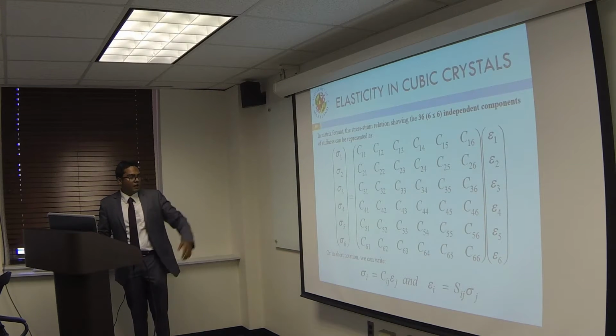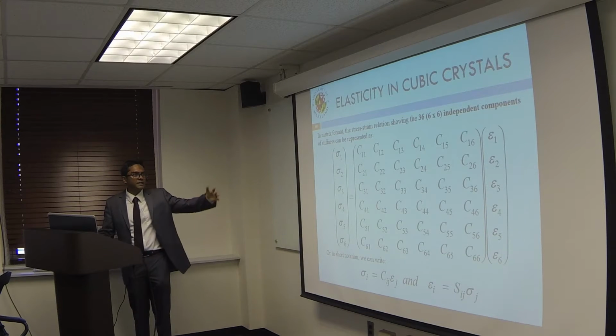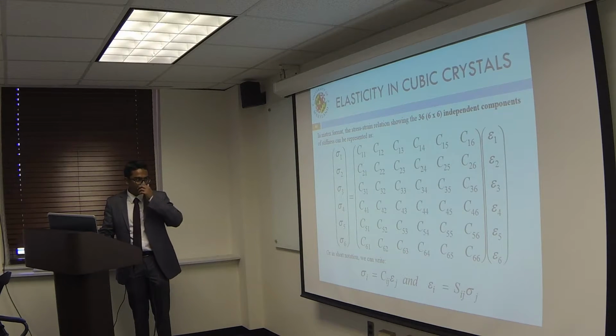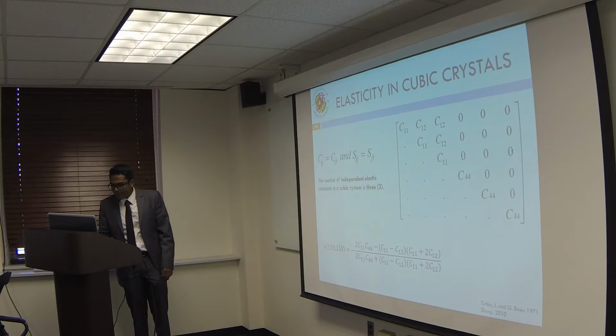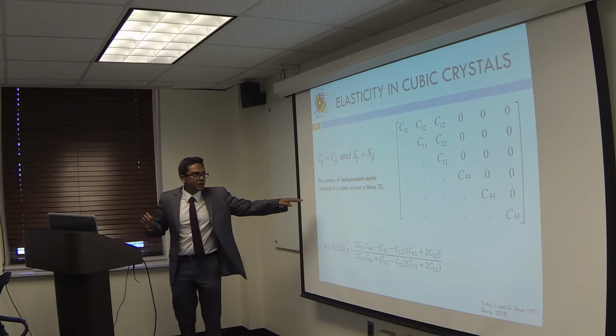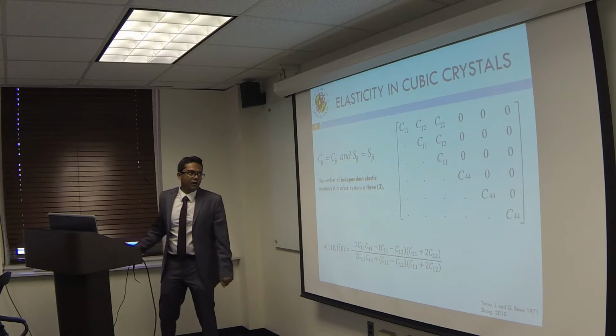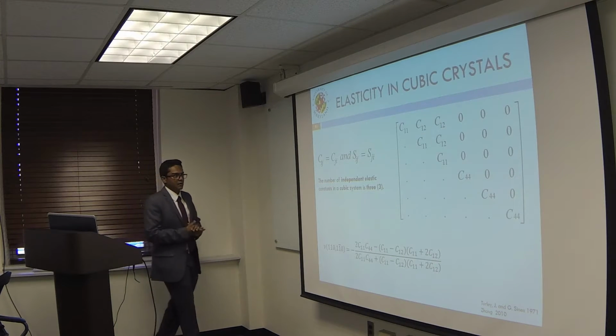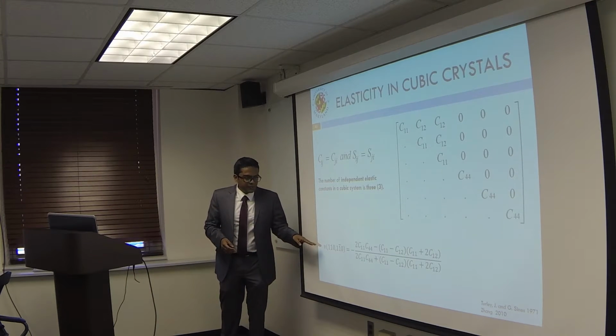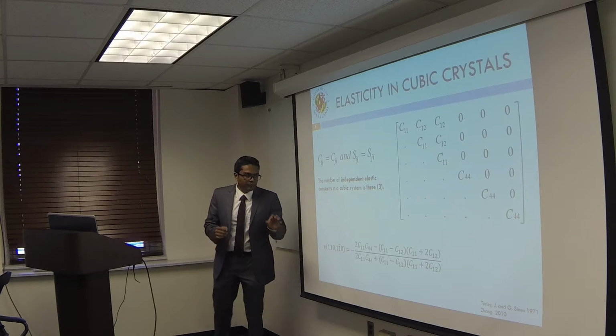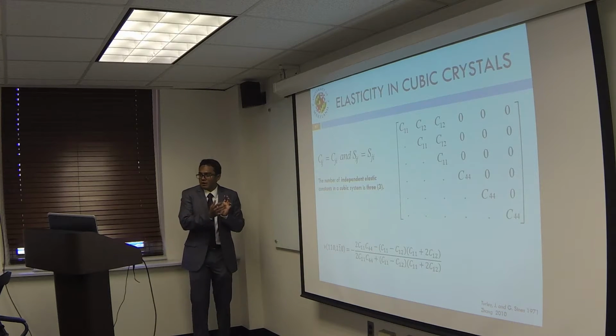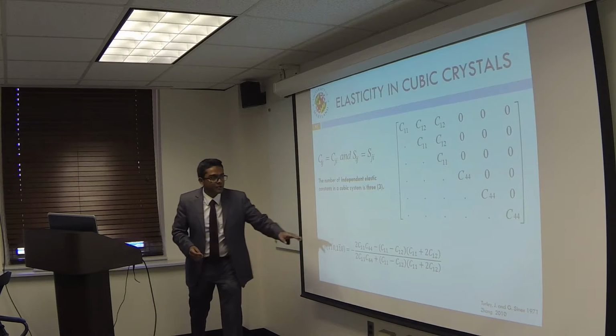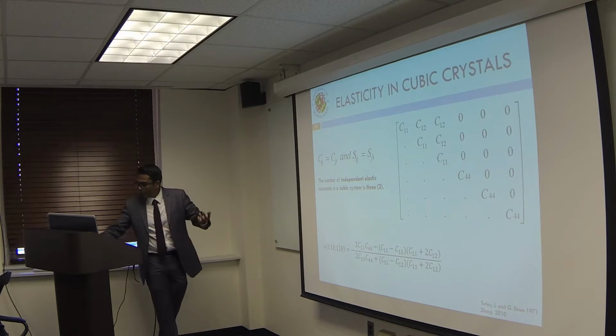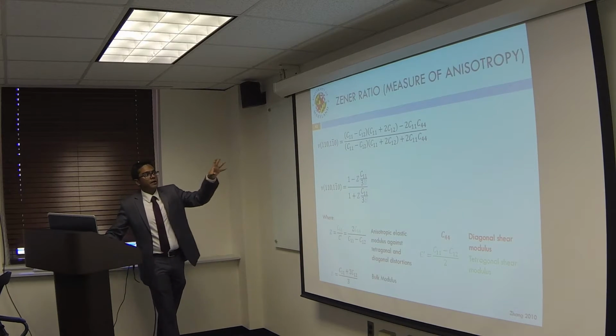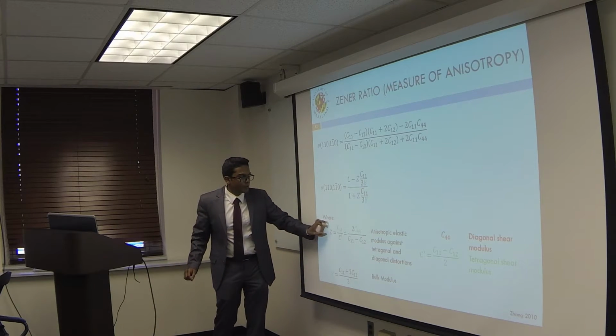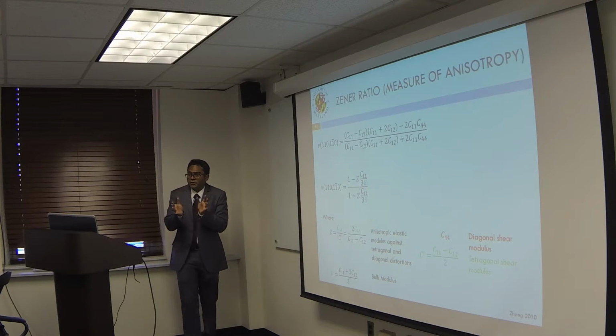So this is just the Hooke's law. You have the 36 independent components for the stiffness. But since we're dealing with a cubic material, we only have 3 independent elastic constants. A previous researcher had derived the Poisson's ratio along the 110 direction in terms of these elastic coefficients. And what I decided to do was to rearrange the terms such that we're able to compute the Zener ratio, which is the measure of anisotropy in the system.